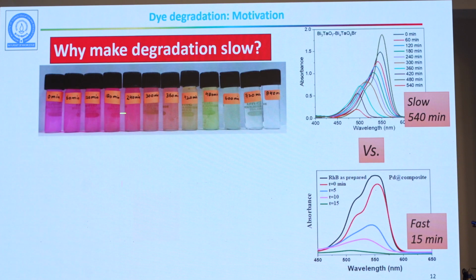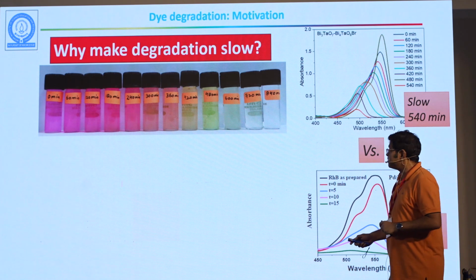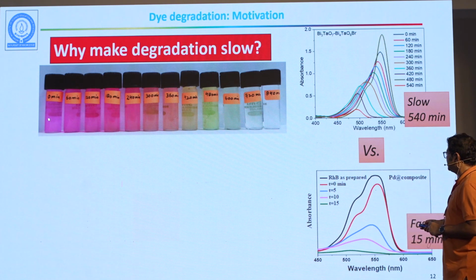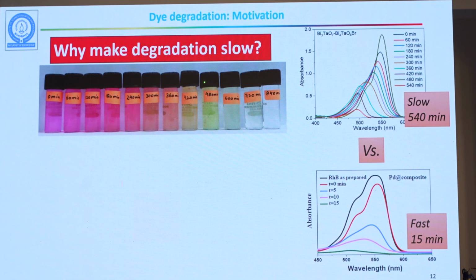So now this is a reaction, and you can see this has gone all the way up to 540 minutes, which is roughly 9 hours. So typical time is 15 minutes. So this is 9 hours, very, very slow reaction. We made it slow. What you see in the process is that you see some color changes. There are beautiful color changes. The red color, the pink color has gone through green color, and the color disappears. So before, conventional system is 15 minutes, and this is about 9 hours.